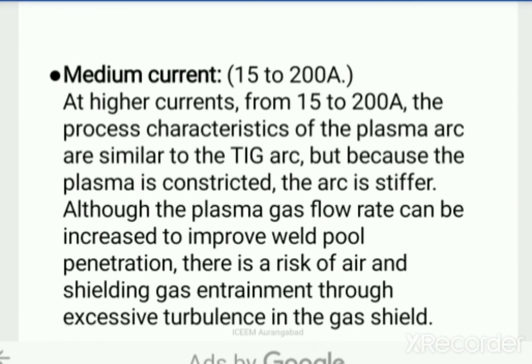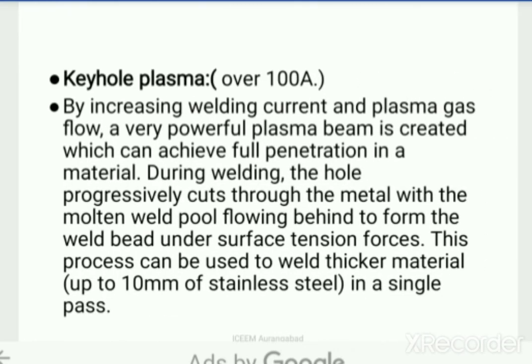Medium current, 15 to 200 ampere. At these currents, the process characteristic of the plasma arc is similar to the TIG arc, but because the plasma is constricted, the arc is stiffer, although the plasma gas flow rate can be increased to improve weld pool penetration. There is a risk of air and shielding gas entrainment due to excessive turbulence of the gas shield.